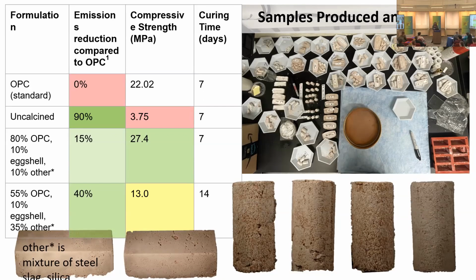This type of cement is called alkali activated, and it has the potential to reduce cement's emissions by up to 90%. We're basing our formulations off of a team at Drexel that has made uncalcined cement with strengths greater than OPC. Unfortunately, we have had not such success in the lab, and we're still working to hopefully crack this formula. The other approach that we've been using is using eggshells to create cement.